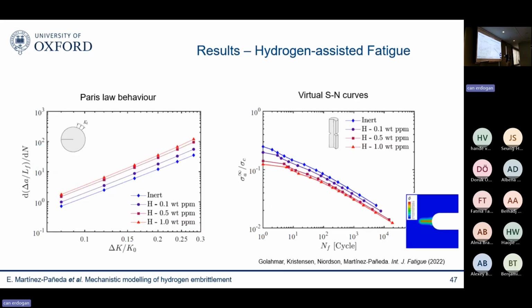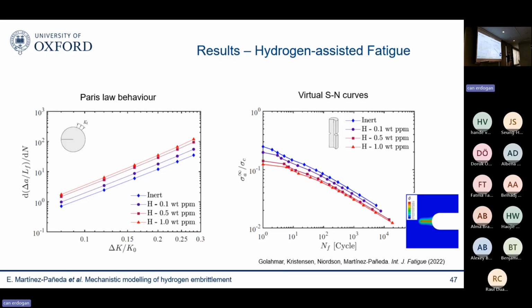And then you can also obtain as an output of the model the Paris law behavior. So we don't give the Paris law behavior as an input to the model. The model tells you what the Paris law constants are as a function of the environment or anything you're interested in. And you can also compute virtual SN curves for any arbitrary choice of environment and geometry, be it a notched component, and applied load and load history. And these, by the way, are cycle-by-cycle calculations, which are very powerful because then you don't have to apply superposition. You cannot apply superposition when you have hydrogen.